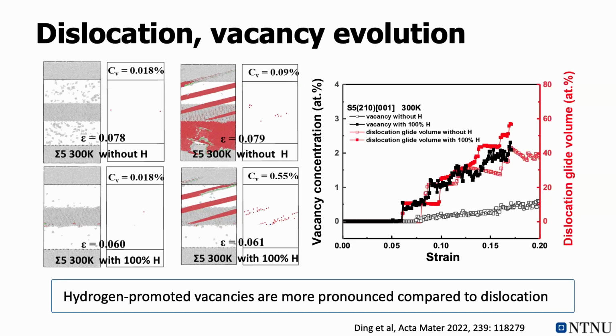And here are the results. If we look at how the hydrogen influences the vacancy concentration and the dislocation gliding volume increase, it's so obvious that it has a significant influence on the vacancy behavior, but not on the dislocation behavior. So that means that hydrogen plays more of a role in the vacancy increase.